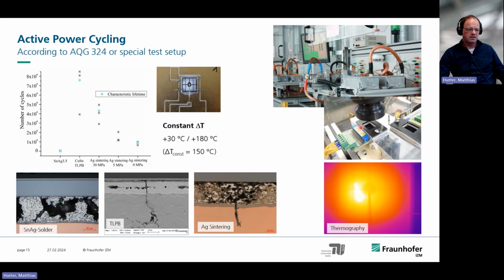We have, of course, to calibrate the temperature, because we really use a constant temperature. So if we go to higher temperatures, then we have a premature failure, and we could not really see then also the failure mechanisms. You see how these joints fail. You see, because it's active power cycling, the joints fail more or less in the middle, but it's not so far away from what you really see if you look at power modules in the field, because also there they are more or less under active power cycling.